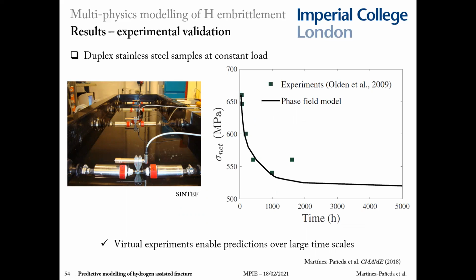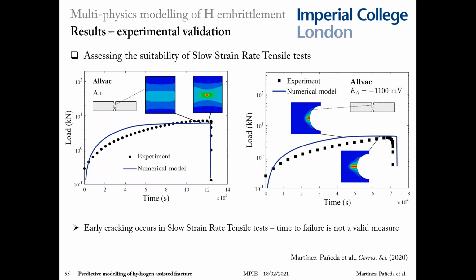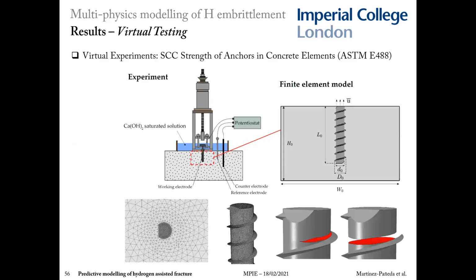But what we can do with our model is not only to reproduce the experiments, but to run simulations over very large timescales so that we can determine the critical stress below which engineers can load their structure safely. And we have also used this virtual tool to gain insight into the suitability of standardized tests, specifically in regards to slow strain rate tensile testing. We learn, as our experimentalist colleagues at the University of Virginia suspected, that early cracking occurs, and this compromises the suitability of what is arguably the most widely used experiment for measuring hydrogen susceptibility. And one can also use this tool to simulate any kind of experiment, minimizing expensive experimental campaigns.